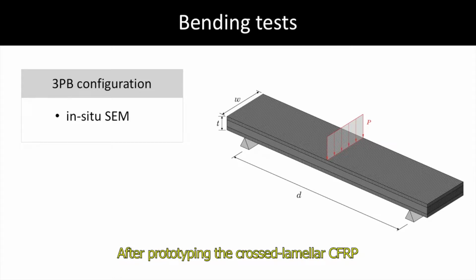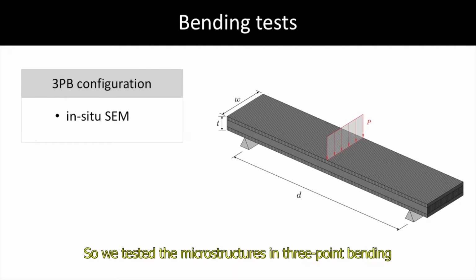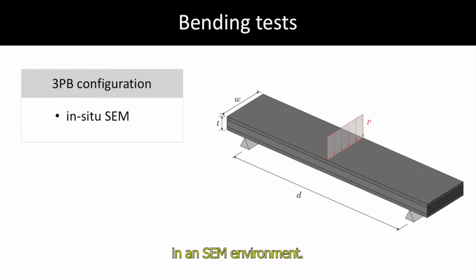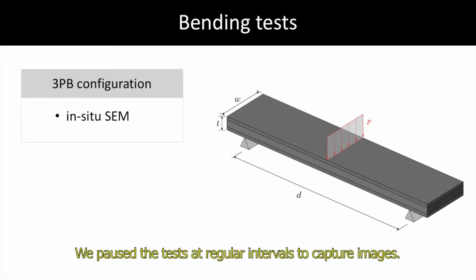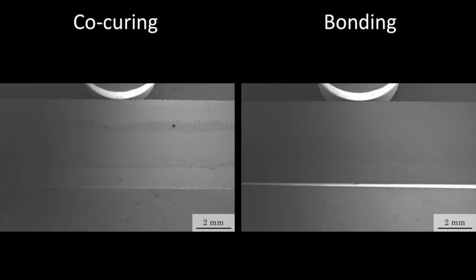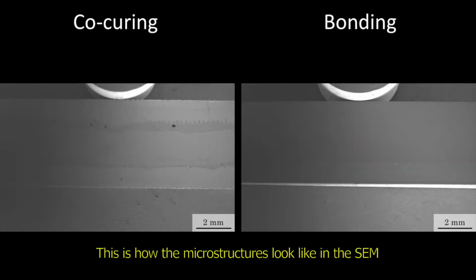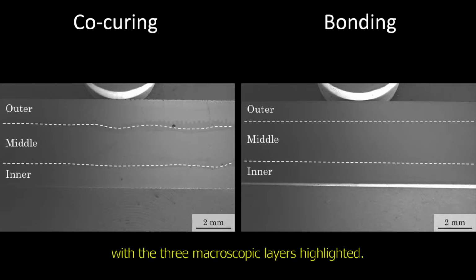After prototyping the crossed-lamellar CFRP using two different procedures, we wanted to know how the microstructures perform when we test them. So we tested the microstructures in 3-point bending in an SEM environment. We paused the tests at regular intervals to capture images. This is how the microstructures look like in the SEM, with the 3 macroscopic layers highlighted.